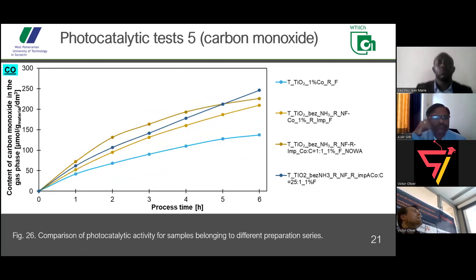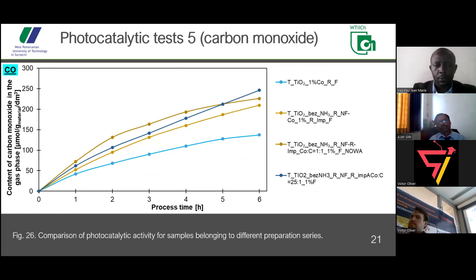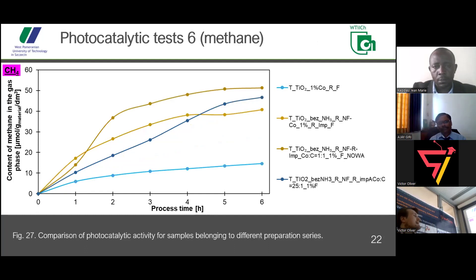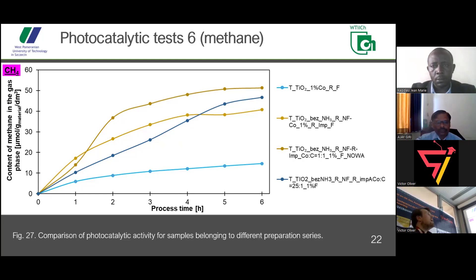The synergistic effect is dependent on the proportion and balance of metal to nonmetal — more metal, less nonmetal appears desirable. The same tendency holds for CO, since cobalt is very selective towards CO. All samples with cobalt tend to perform better in terms of CO production. For methane, we see that introducing more carbon to the system implies greater selectivity towards methane.